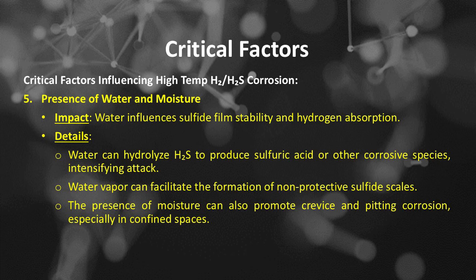Number 5 is presence of water and moisture. The presence of water and moisture impact: water influences sulfide film stability and hydrogen absorption. For details, water can hydrolyze H₂S to produce sulfuric acid or other corrosive species, intensifying attack. Water vapor can facilitate the formation of non-protective sulfide scales. The presence of moisture can also promote crevice and pitting corrosion, especially in confined spaces.